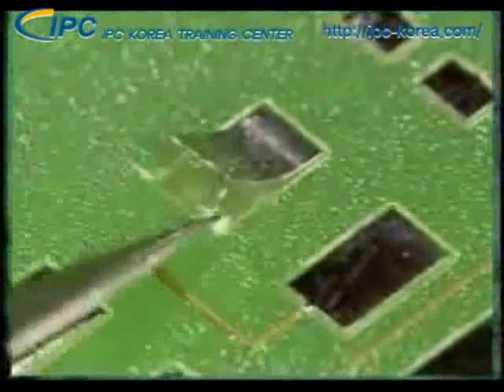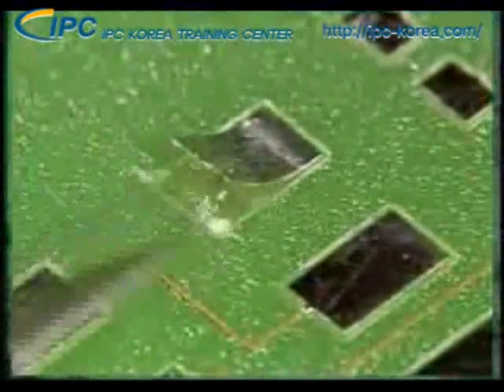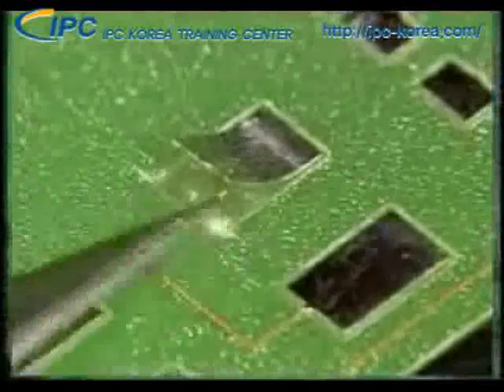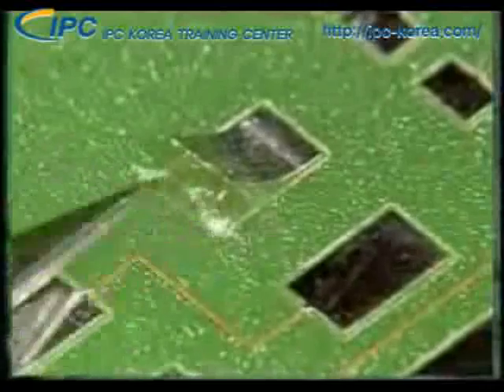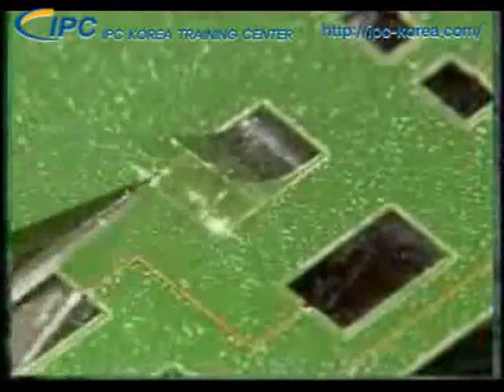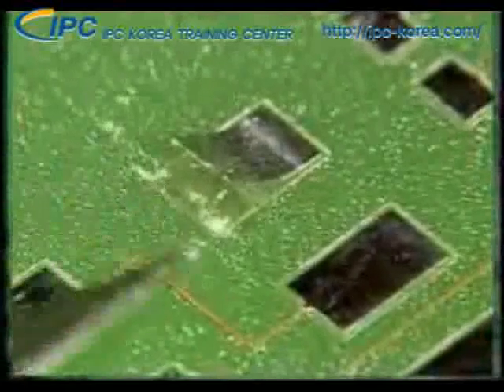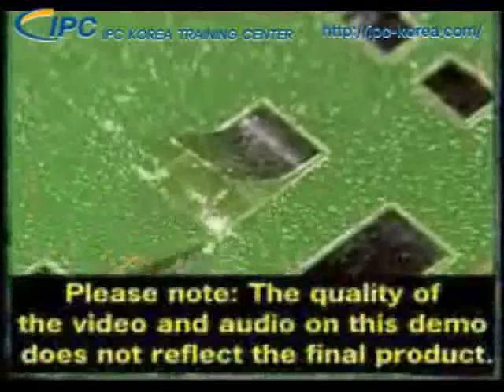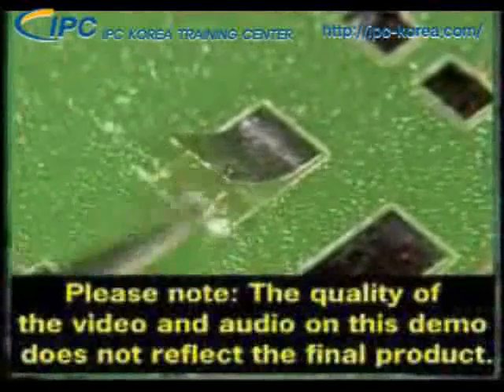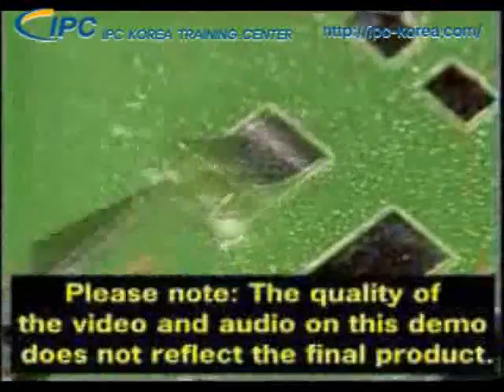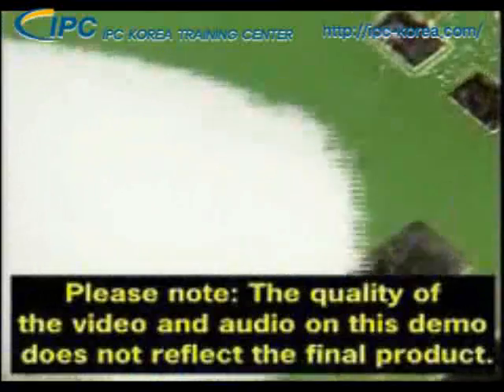First, use a utility knife to scrape away any residue, contaminants, or obstructions that might prevent the lifted land from making full contact with the board surface. If solder masking is close to the repair area, clean it away to allow access for the bonding tip. After removing any contamination and solder mask, re-clean the area using your chemical cleaner and a brush or swab. Then blot dry using a dry wipe.